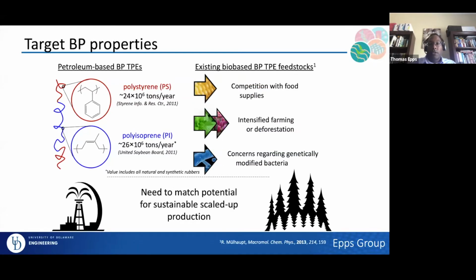If I look at this in another way, there's another problem. If I start thinking about polystyrene, and not saying we're going to replace all of it with our bio-based materials, you're looking at something on the order of 20-ish million tons a year in production. If we look at our existing bio-based feedstocks, we have things like polylactide, and there's the opportunity to compete with food supplies, which is not something we'd like to do. The alpha-methylene gamma-butyrolactone takes intensive farming and deforestation. I haven't talked about yield yet, but one of the key things when getting that monomer for the lactone-based polymer is that I get it at 1 weight percent yield from tulips.